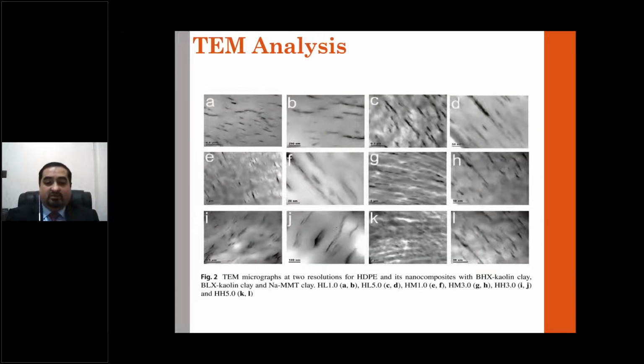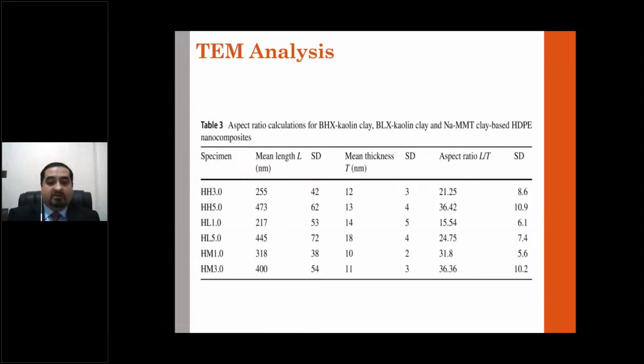Now the TEM results showed good dispersion and distribution, but also the presence of a few agglomerates. But most of the time the tortuosity path was there, and along with the tortuosity path, good dispersion and distribution of nanofillers within our material was present. We then looked at the overall aspect ratio calculations by utilizing the TEM results along with ImageJ, and we found that we were able to get a good aspect ratio.